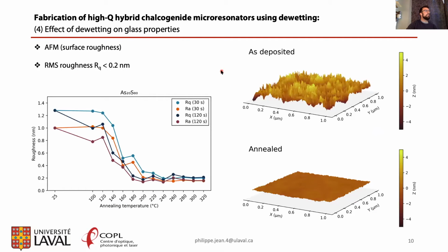Okay, what is even more interesting, I think, regarding dewetting, and to me a strong result of this study, is the resulting roughness after dewetting. So that's what you can see here. We used AFM to measure the surface roughness of the glass deposited on the microscope slide, both for 30 seconds and 2 minutes. And what you can notice is that as the temperature increases and we get into the range of temperature that actually induces dewetting, there's a drastic reduction of the surface roughness.